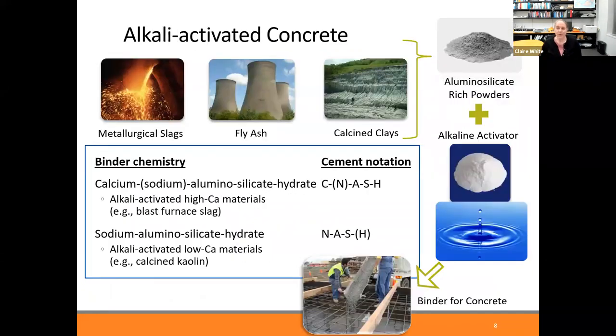Also, we work on alkali-activated concrete. This type of alternative concrete you can make using metallurgical slag, so actually amorphous glasses that are in these metallurgical slags. You can use fly ash, which is a byproduct from the coal industry, and calcined clays I've mentioned before. But say if you add calcined clays to water, they're not going to react.